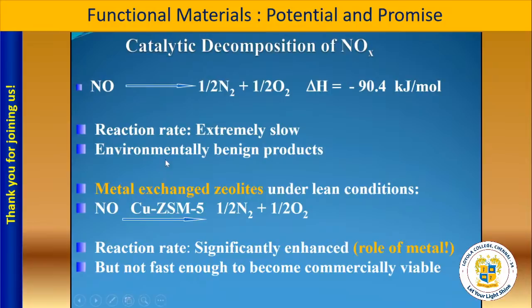ZSM5 alone does not do anything. But when transition metal oxides are loaded on the aluminosilicate zeolites, they act as a catalyst and significantly enhance the rate of reaction. However, the reaction rate is still not large enough to make this process commercially viable. At this point, essentially, this calls attention to two things. But there is hope: what is the role of zeolite and what is the role of transition metal